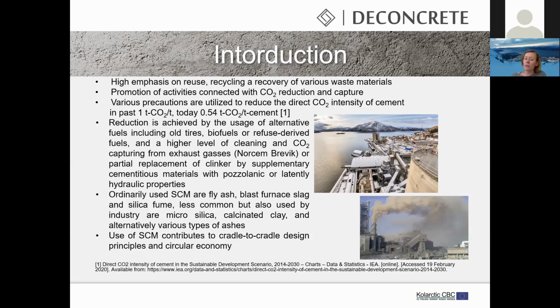For example, in Norway there are no sources of fly ash, and presently for Norcem, which is the cement producer in Norway, the fly ash is supplied from Turkey, which has quite a significant impact on the CO2 due to the shipping of the supplementary cementitious material.